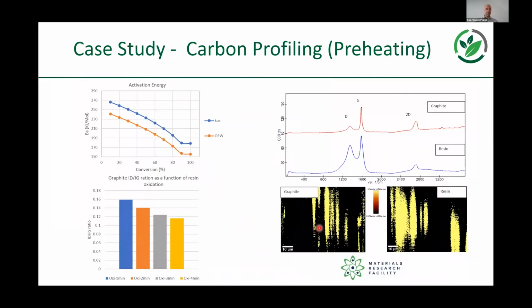But just to give you an idea of some of the outputs from the atmospheric behavior of the material, what we've been able to do is to develop, using thermogravimetric analysis and some of the heat treatments that we've been doing, a method to rapidly assess, via non-isothermal, i.e. through continuous heating rate, and model free kinetics, so a simple and easy to implement kinetic approximation of the material, how the activation energy or the barrier to oxidation in these materials is changing as a function of the conversion.